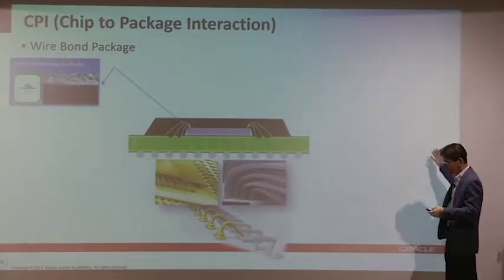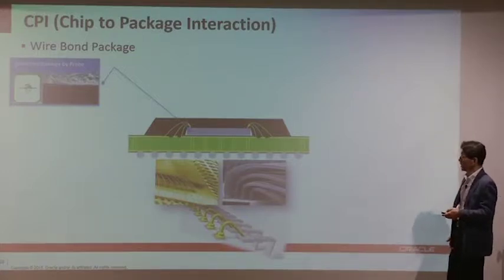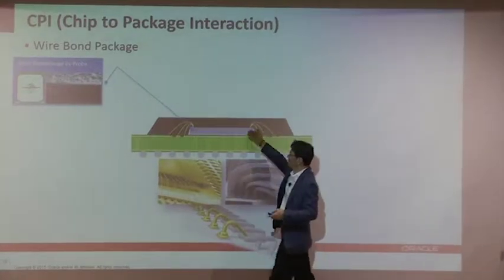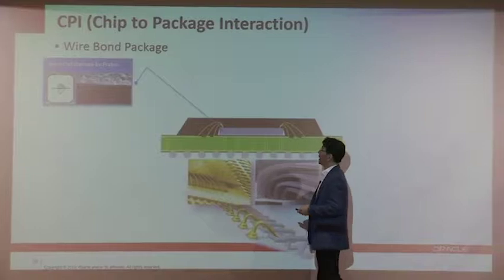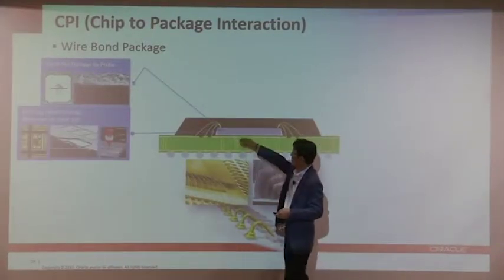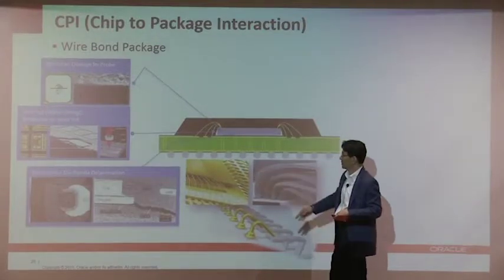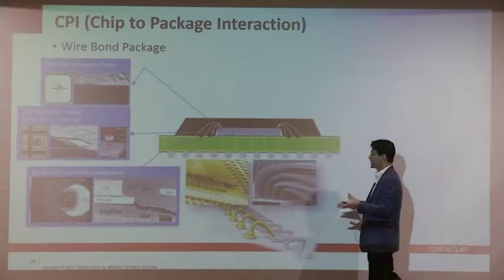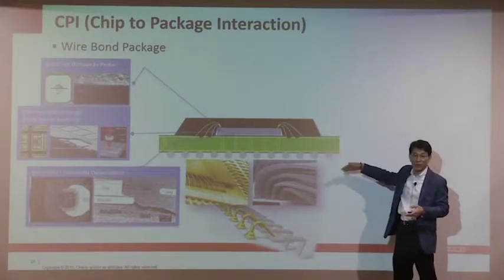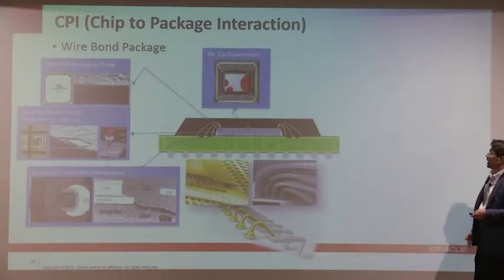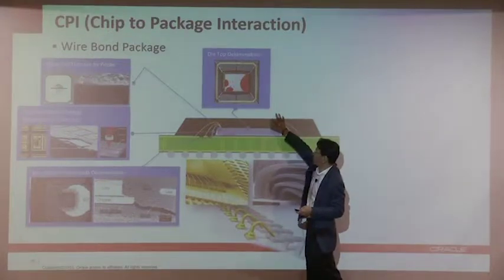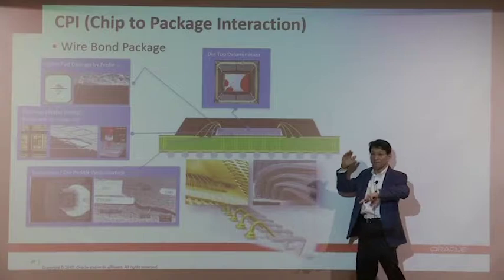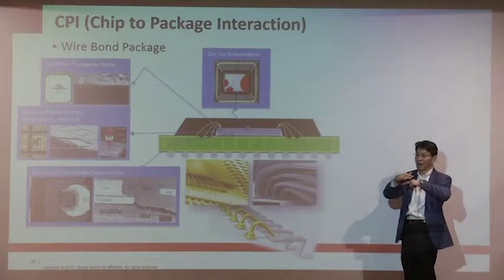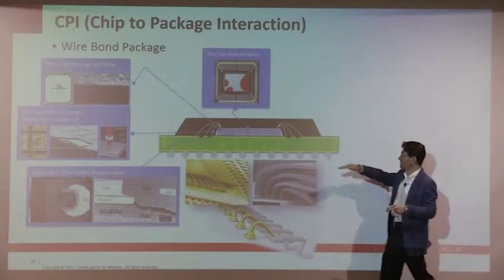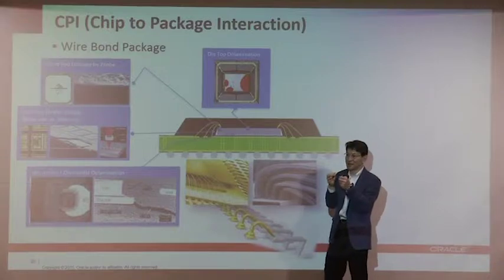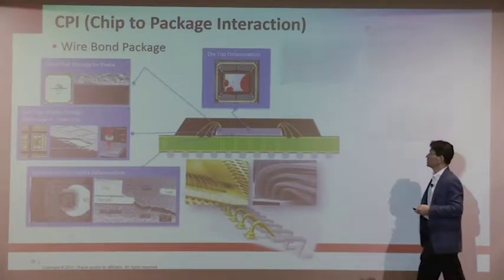For wire bonding and flip chip, next slide, and then the other slide, 2.5D, they always have similar types of challenges. Silicon damage during dicing, and during wafer probing, some pad damage, which moving forward is going to create die attach or substrate delamination during the actual application. Die top delamination between the molding compound, encapsulant, and die surface, because they are different materials. So eventually the shrinking and then the relaxing is going to be different. So the interface is going to be subjected to very high stress, and boom, critical failures.